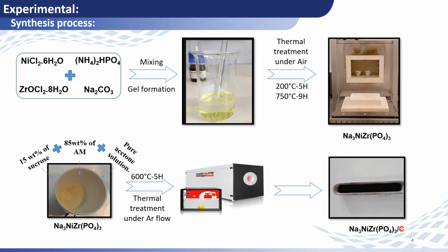Our phosphate-based material was synthesized through a simple sol-gel method. Firstly, the following raw materials were mixed and stirred in an aqueous solution, then heated up at 60 degrees Celsius until complete evaporation and gel formation. After that, we proceed to a calcination for 9 hours at 750 degrees Celsius with intermediate grinding.